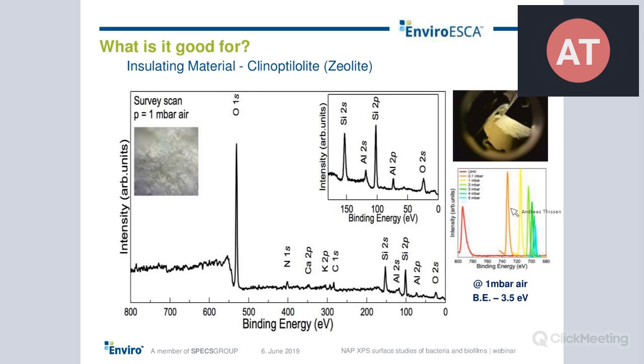But as soon as you let in 1 millibar, 2 millibar, or even higher pressures of gas, you see that it shifts back to the original position, but most important is that it also gets very symmetric and you get a very narrow line so that you really can do chemical analysis here. And the criterion to find out what is the good pressure is where the line width is the smallest. And you see that you don't have to go to 5 millibar or higher. You can pretty easily work under 1, 2, or 3 millibars, where you also see that you do not lose a lot of signal due to the inelastic scattering in the gas phase.